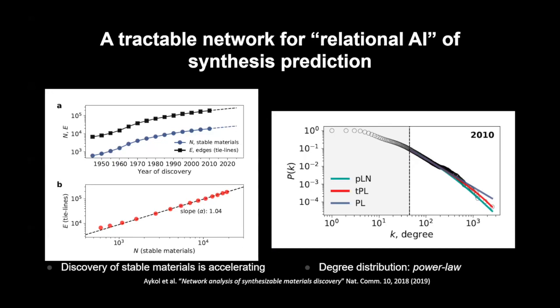So how are we going to make a connection between this network and synthesis? Well, many of the compounds in our network are actually experimentally observed compounds. And these are taken from databases like the ICSD. What this means is that there's a timestamp, a year associated with the discovery of these materials. There's a reference to their discovery and a year in which they were discovered. And what this means is that we can associate a year with every node in our network. Okay? This means that we can actually rewind time and say, what did this network look like in 1950 or 1960 or 1970? And we can follow the evolution of stable materials in this network as a function of the year, and also the number of stable tie lines and things like that.